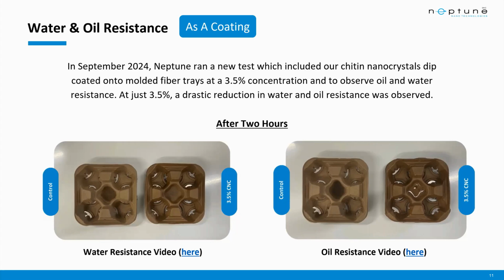So as you may know, a typical molded fiber tray is made from recycled fiber. So they have large fiber size, they have large pore size, and because they're molded fiber, typically they're not treated with sizing agents, no other chemical modifiers involved. So in their naturally existing form, they are highly susceptible to water and oil. It will typically instantly absorb all the liquid and the whole tray will turn into mush, as you can probably imagine. But once the chitin nanocrystal coating is applied, it was able to resist water and oil penetration for multiple hours. And we captured all of our testing on video, which is embedded as a link here, but it's also live on our YouTube channel as well.